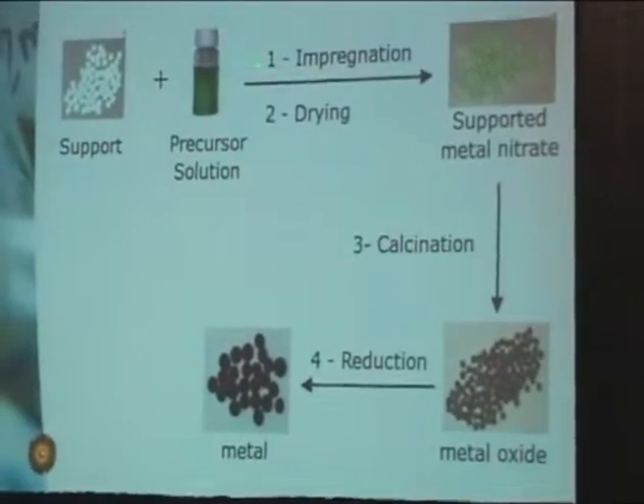So we discriminate between impregnation of the solution onto the support, then drying to evaporate the solvent, which gives us the supported metal salt, for example nickel nitrate in this case, and after calcination or thermal treatment we get metal oxide particles on our support, and after reduction we observe the metal nanoparticles.